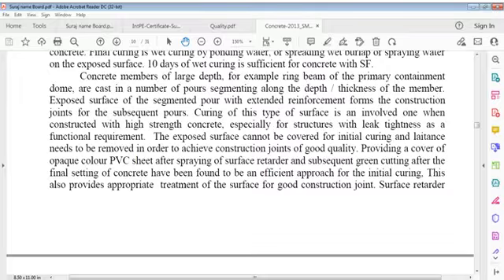Curing of this type of surface is an involved one when constructed with high strength concrete, especially for structures with leak tightness as a functional requirement. The exposed surface cannot be covered for initial curing, and laitance needs to be removed in order to achieve construction joints.